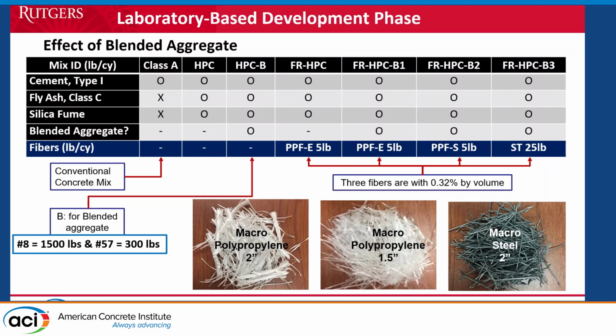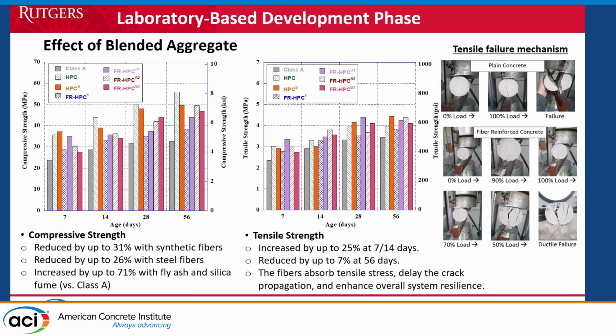We also tried different amounts of fiber. Unlike in the lab, where you can put in a lot of fibers, the workability will not be good, and we tried that. We found there is an optimum point: how much is recommended by the manufacturer, but also how much gives a workable mix for finishing and pumping. We had to keep that in mind. So we ended up with different mixes, some with 5 pounds of fiber per cubic yard. E is the type of fiber from Euclid Chemical Company, and S is from Sika fibers, and we also had steel fibers there.